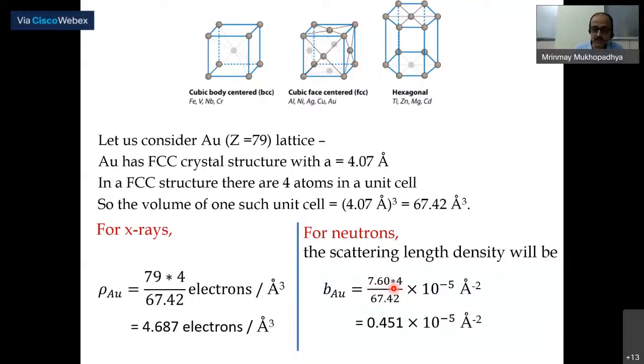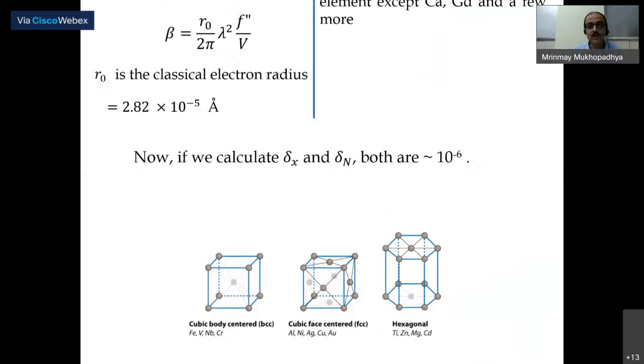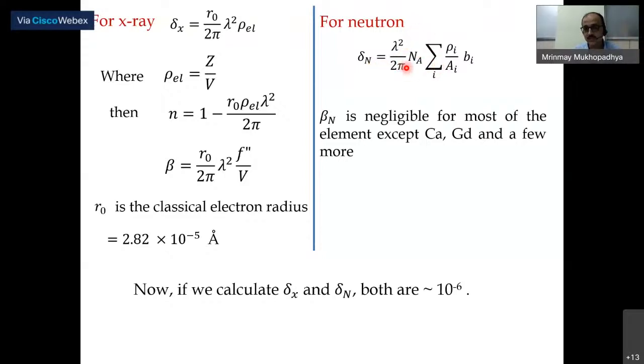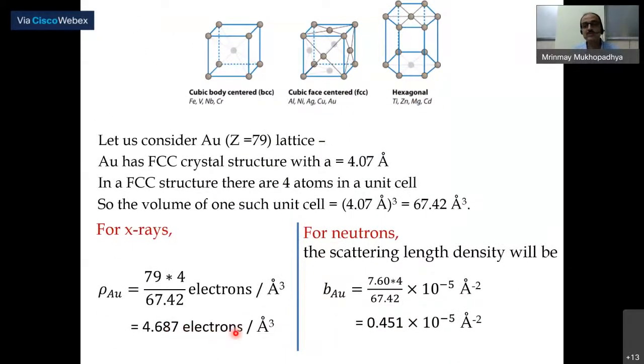That's all, basically. You can do similar things, and you can see 0.451 times 10 to the power minus 5 Angstrom square. Here you can see 4.687 times 10 to the power electrons per Angstrom cube, but you are forgetting that here the R0 term is multiplied, and there the R0 term is not there. If you multiply by 2.82 times 10 to the minus 5, the scattering will be 2.82 times 4.687, whereas it is 0.451. So the same gold for X-ray will give a lot of scattering, while for neutrons it will not give that much, because the scattering length density is small.